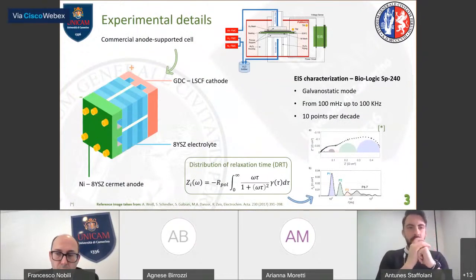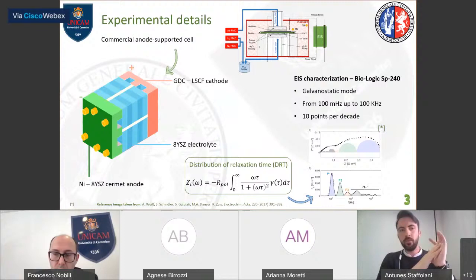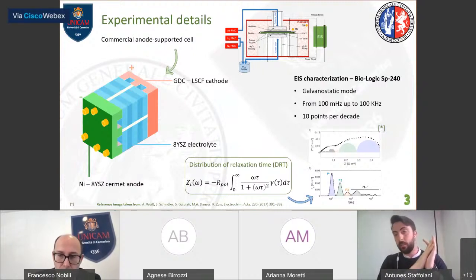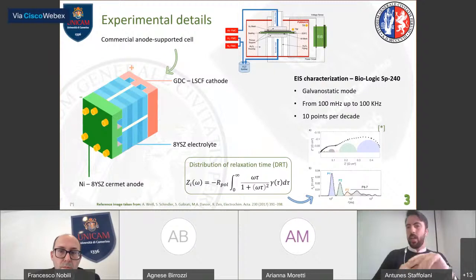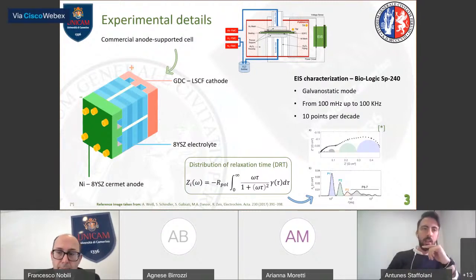And some small experimental details: the cells used in this work are commercial anode-supported cells with a nickel, yttria-stabilized zirconia anode, a yttria-stabilized zirconia electrolyte, and a gadolinium-doped ceria, lanthanum strontium cobalt ferrite cathode. And regarding impedance analysis, since there was no reference electrode inside the cell, we used the distribution of relaxation time to decouple all the processes occurring inside the cell.